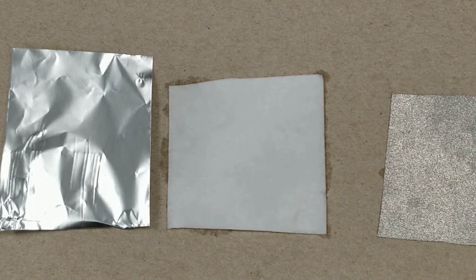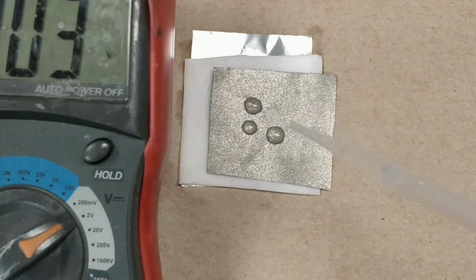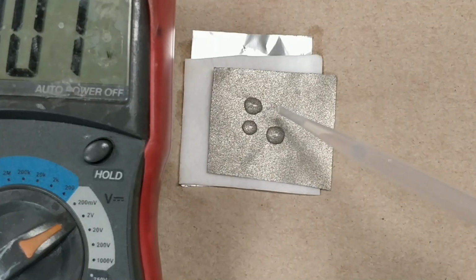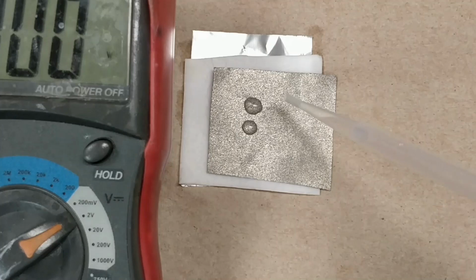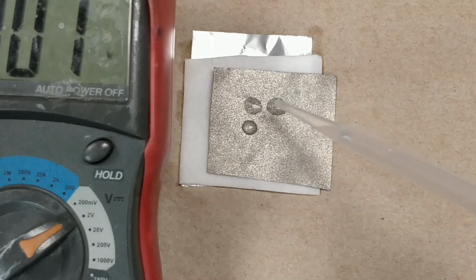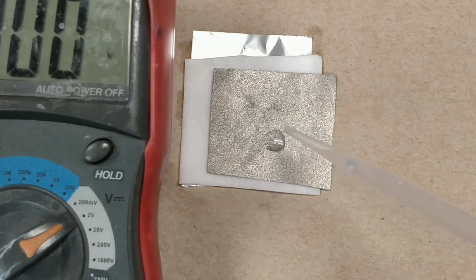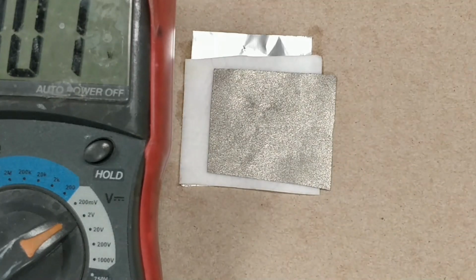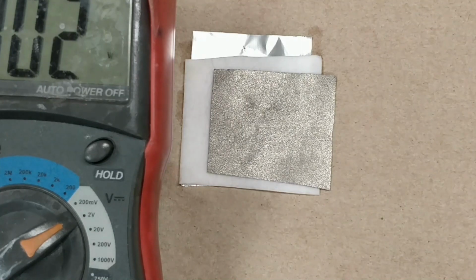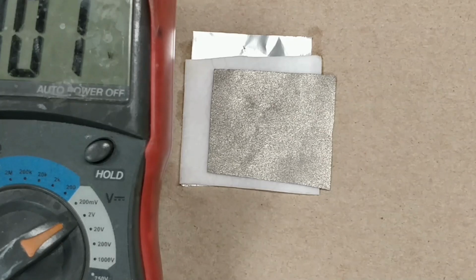Note that as the oxygen cathode is gaseous and is virtually limitless, this fuel cell reaction is only limited by the amount of available aluminum metal. Thus, these cells can be built into very lightweight designs and can operate for a long time. The fuel cell can easily be assembled by stacking the separator and nickel foam on top of the aluminum anode and adding a few drops of the salt water electrolyte.